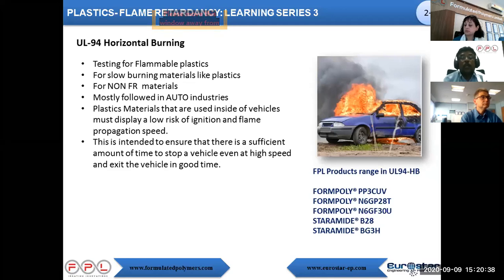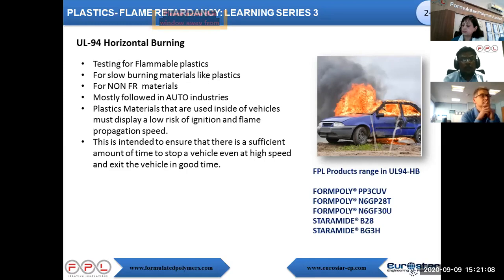Now we move on to the horizontal burning test. In the horizontal burning test, the specimen is clamped in a horizontal position. The HB test is widely followed in the auto industry. It tells the rate of burning of the plastic material used. It helps the auto industry in a big way. The rate of burning of material helps to calculate escape time for passengers in vehicles. HB rating is normally required for decorative items, attended household items, hair dryers, etc. It is applicable for all products, irrespective of flame retardant or non-flame retardant.